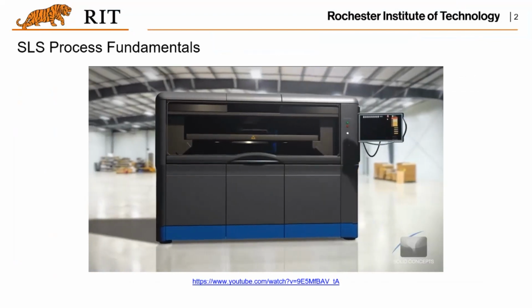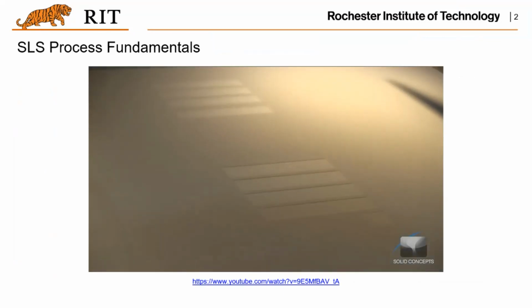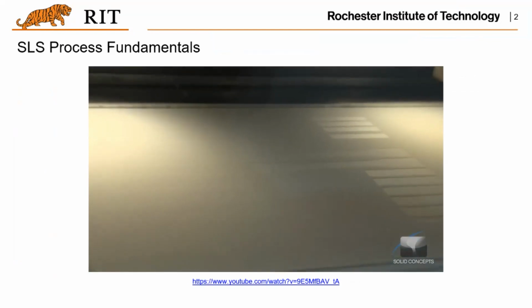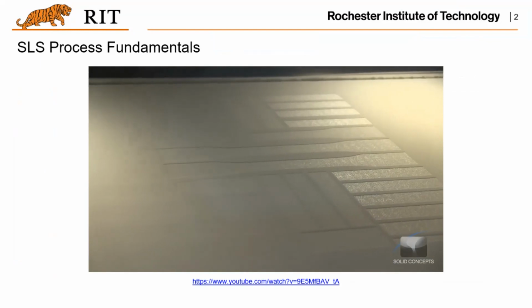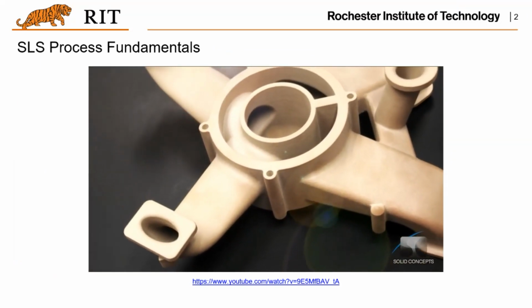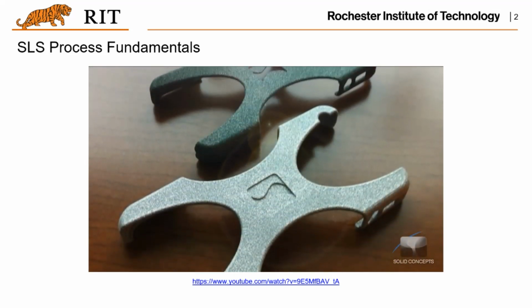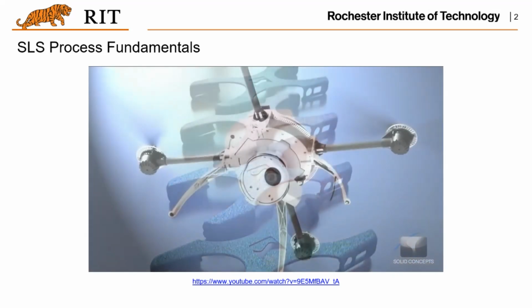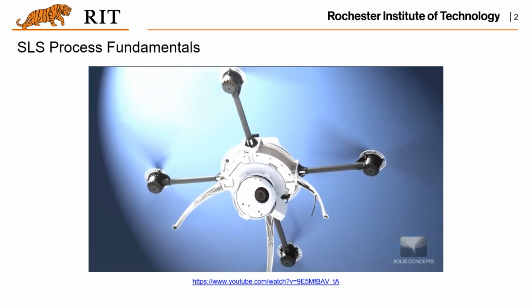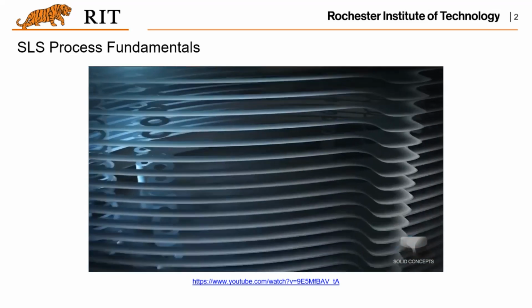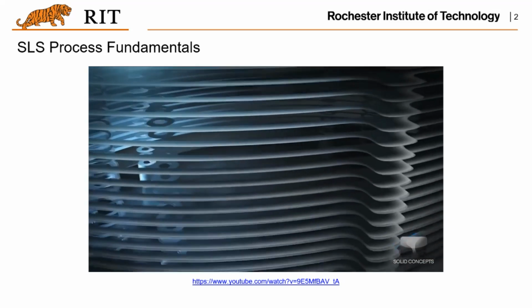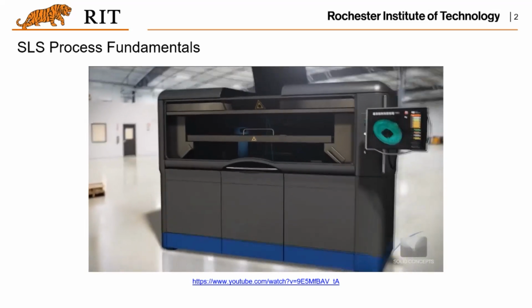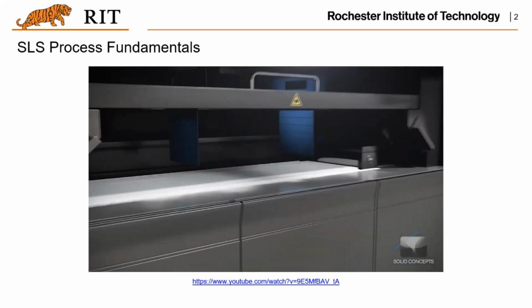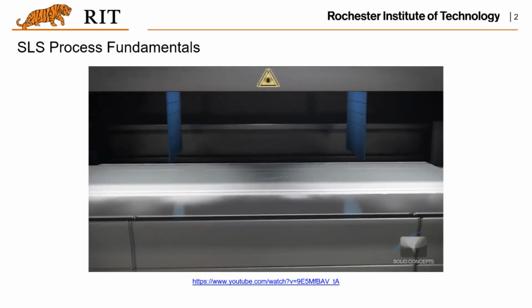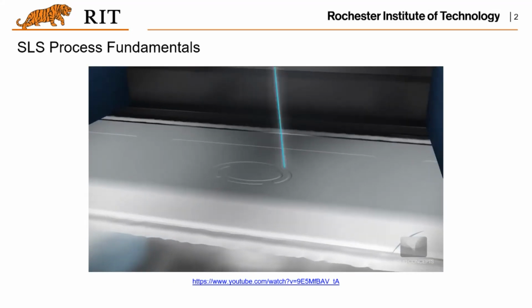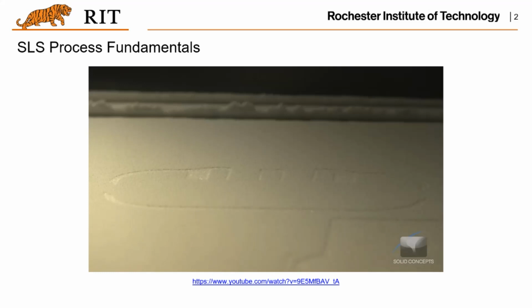Selective laser sintering, or SLS, is a rapid prototyping technology that turns 3D CAD data into physical parts in a matter of hours. SLS is an additive manufacturing technology that uses powdered nylon 11, nylon 12, and PEEK materials. Parts produced are lightweight, highly durable, and both heat and chemical resistant, making SLS an excellent choice for producing production parts without the expense of tooling. The SLS process begins by splitting 3D CAD data into thin cross-sections or layers. The data is then transferred to the SLS additive manufacturing equipment. The machine then begins to create the first layer. After a leveling roller spreads a thin layer of powdered material across the powder bed, a CO2 laser traces the cross-section on the material. As the laser scans the surface, material is heated and fused together.